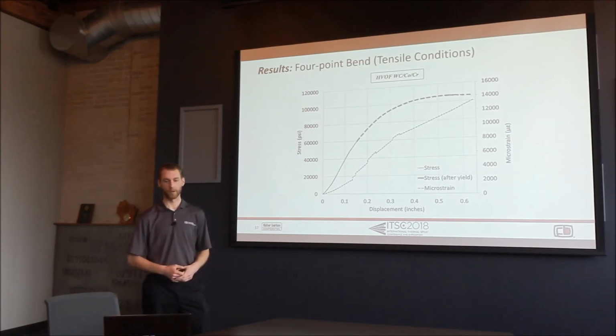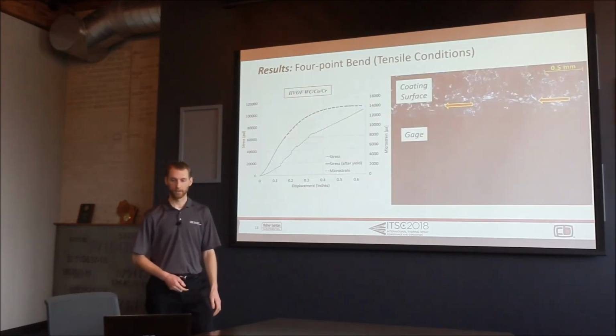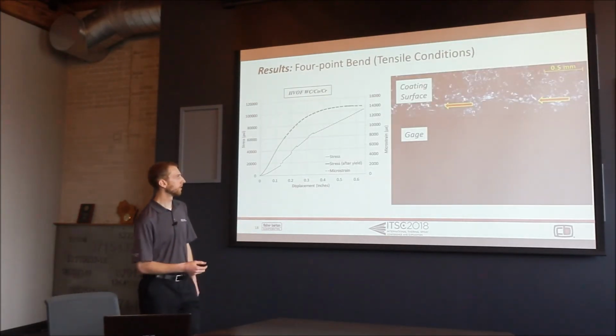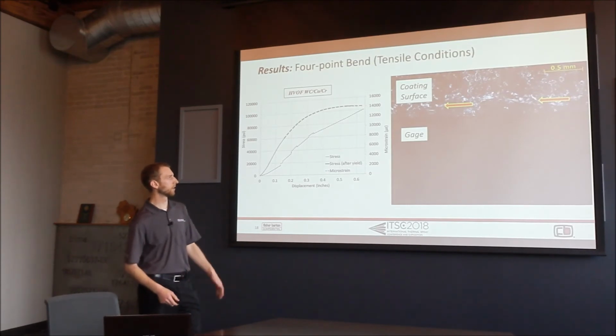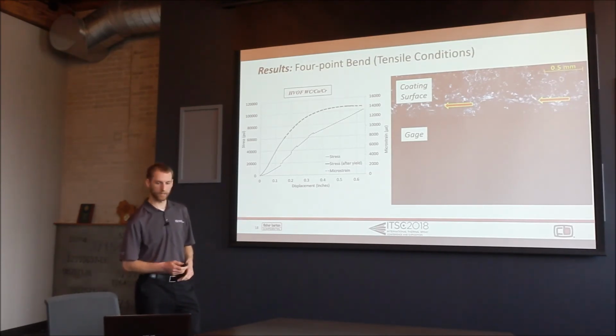So that's really the main takeaway from all of this data. Now it is different loading, but this is closer to true functional behavior from our perspective. And this is just confirming we do see some of those cracks looking at the top surface of the coating after the test.